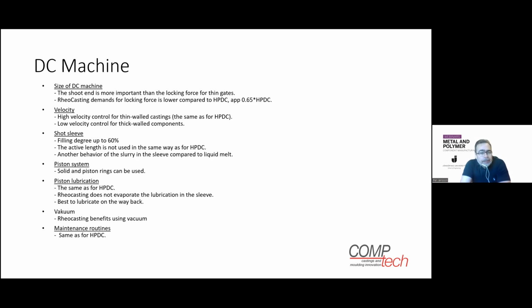We can see that we use the same piston systems that we use in conventional high pressure die casting, both solid and piston with rings can be used. So there's no difference. I would also like to say that the shot sleeves we are using are the same material and same type of shot sleeves that we use for conventional high pressure die castings.